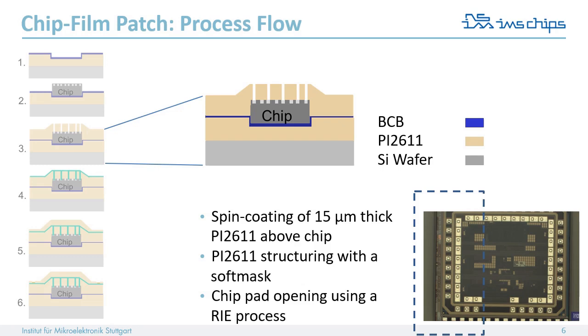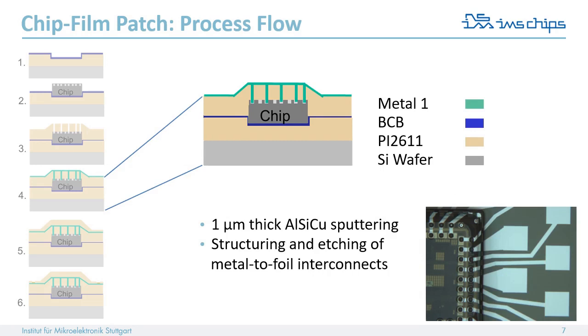Then the polyimide is structured photolithographically by using a photoresist soft mask and a laser direct writer, which provides an accuracy of less than 5 micrometers. The chip pads will be opened by etching of the polyimide, which is shown here highlighted in blue on the close-up view. The connection from chip to foil level is formed by AlSiCu alloy metallization, structured and dry etched afterwards. The silver colored chip to foil interconnects are shown below on the right-hand side.